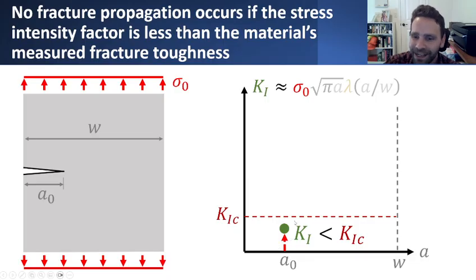And that happens to be the case anytime we have the stress intensity factor less than some critical value, the K1C, the fracture toughness of the material. So as long as we can increase this value sigma naught to increasing values of stress, and as long as the resulting stress intensity factor stays below this critical value of the fracture toughness, then the crack isn't going to grow. And it'll look on the diagram kind of like we have this K1 measurement at the same value of A naught, the initial crack length, and it'll just be kind of increasing. And as long as it's below this critical threshold, then there's no crack growth occurring.